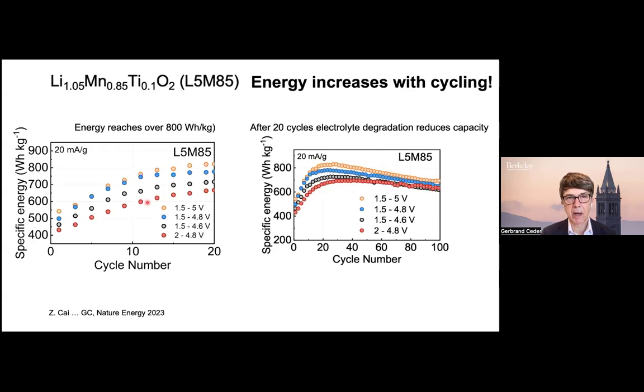One thing about the high manganese content materials is that they have sort of unusual electrochemical behavior. If you take a rock salt, this is a low lithium excess rock salt, high manganese content, right? So this is manganese 3 plus all, so you can do all the redox capacity on manganese. And about 10% titanium stabilizer, this is no fluorine. When you cycle these materials, independent of the voltage window over which you cycle, they actually increase their specific energy with cycling.